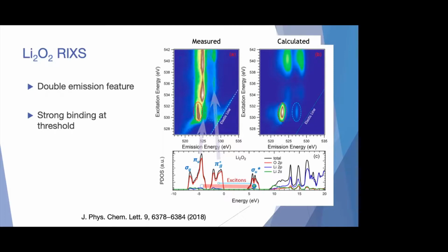Yeah, no, to go after actually looking at this, you would need to go beyond. You would have to actually calculate the cross sections. Yeah. Electron phonon cross sections. And there's been some more recent work on this. Electron phonon vibrations are very well known and easy to do in finite systems, with countable modes. There has been recent work on trying to do these sort of dynamic RIXS in more extended systems. There's been success in aqueous systems, but there I would claim that those are just messy molecules. I'd have to look up citations to get back to you. But specifically within the OCEAN code, no, there's no way to access these sort of dynamic vibrational effects.